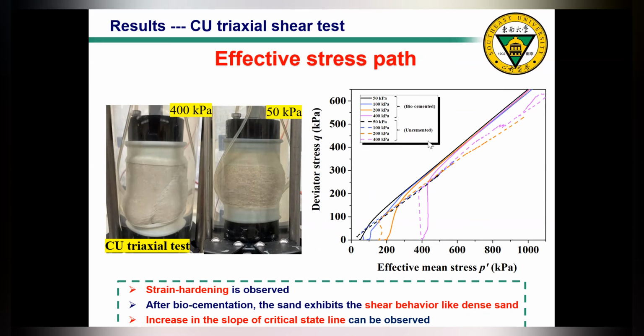Then on the right-hand side graph, this is the effective stress path graph. On this graph, the dotted lines represent the uncemented, the clean sand, and the solid lines represent biocemented sand. Here we didn't vary other parameters like cementation solution concentration, treating time, and so on. We only pick one fixed cementation level. From the effective stress path graph, firstly, we can see that for both uncemented and biocemented sands, they exhibit strain hardening behavior, because it's a CU test.